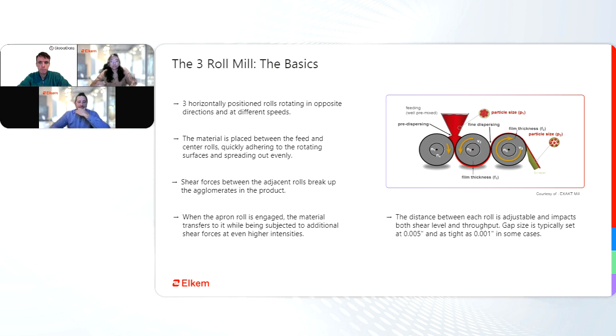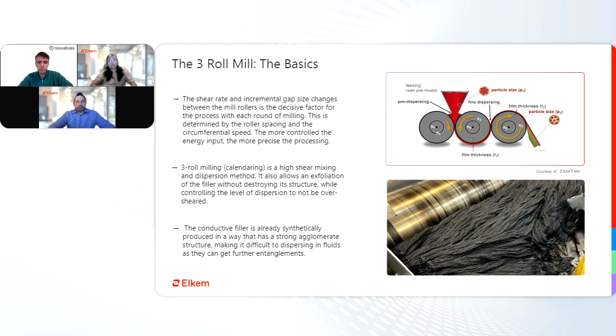These rolls can be adjusted by controlling the speed and gap, and the gap can go as small as 0.001 inch. Now, going deeper, the shear force being applied is very important. The changes in gap size between each of the rolls are decisive factors in the process for each round of milling. Precise controlled energy input will equate to precision in processing, essentially. The high shear rolling allows the fillers to disperse into the matrix without destroying the carbon nanotube structure. Control of gap and speed will control the level of dispersion to not be over-shearing the product itself.